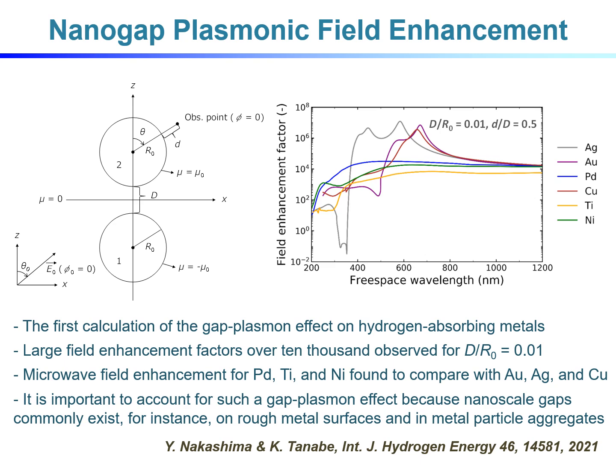Again, we believe that it is important to account for such a gap plasmon effect because nanoscale gaps commonly exist, for example, on rough metal surfaces and in metal particle aggregates. For simplicity, we calculated for spherical particles, but combination of this gap plasmon effect with the previous nanoparticle nanoshell effect and the sharp tip lightning rod effect would provide further field enhancement.